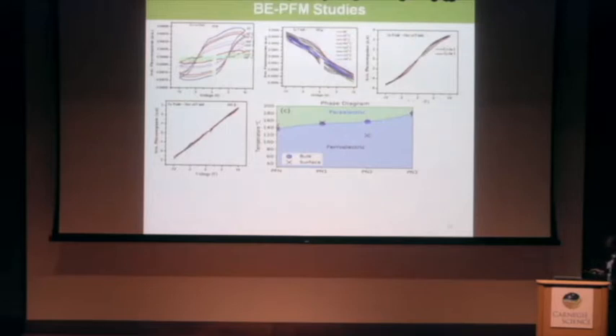So we have carried out some temperature dependent piezo response measurements in order to corroborate the bulk ferroelectric phase transition, and this is the temperature-induced ferroelectric phase transition. As the temperature increases, the piezo response decreases, and above 125 degrees Celsius the piezo response vanishes, in both cases, out of field and in field. This is the room temperature in field minus out of field. It is nonlinear, and in the in field minus out of field measurement it is highly linear, meaning there is no periodicity above the phase transition temperature.